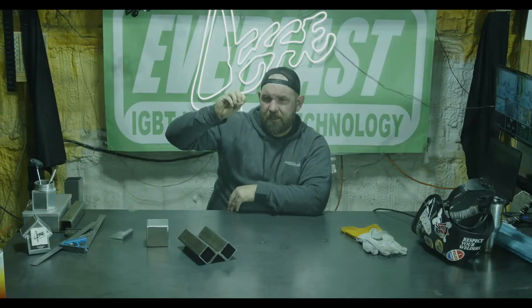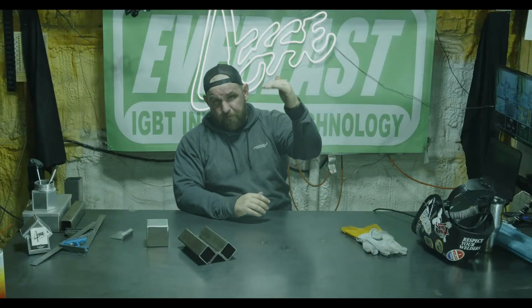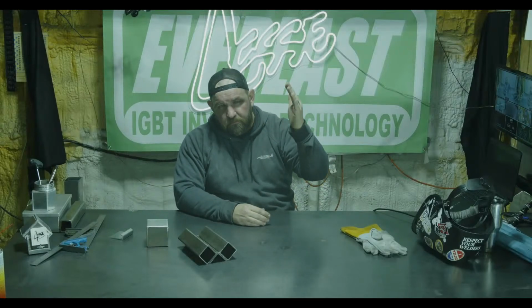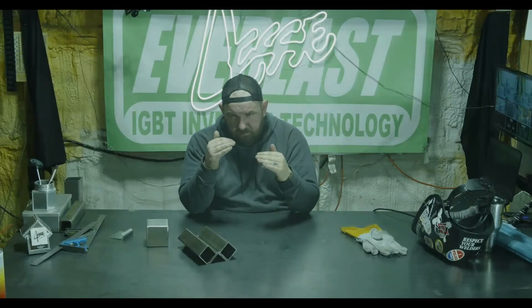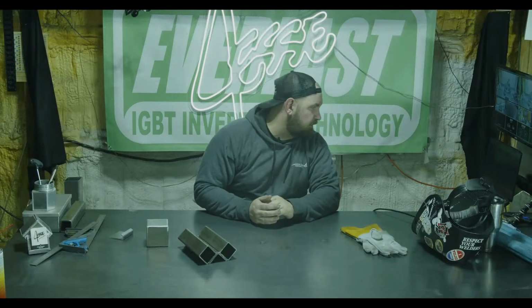I'll generally set it to a 50-50 balance, like 50% on, 50% off, but I'll set my DC electrode negative background amperage to 100%. So if I'm running 200 amps on the machine, my on time and my background amps are both the same. If you need a little more heat, you can go 40% on time, 60% background, and that'll give you more DC electrode negative. It'll be a little bit dirtier unless you're running helium. But the whole point of advanced AC pulse is to let you weld thicker aluminum with a smaller machine with argon, just because helium's so expensive.